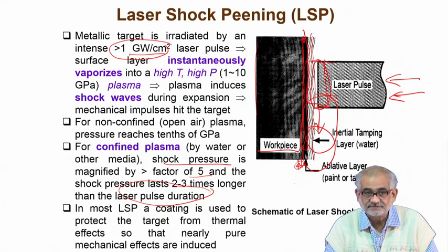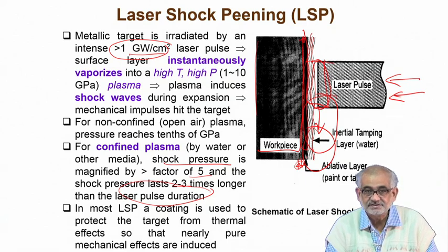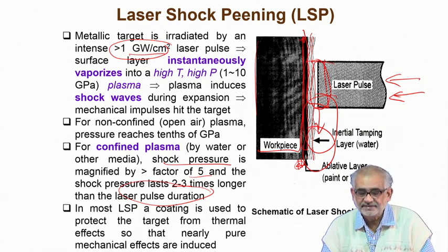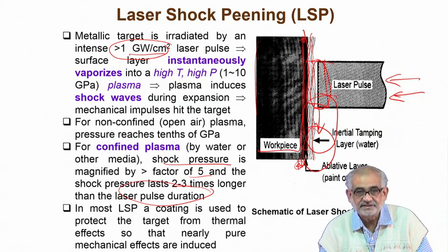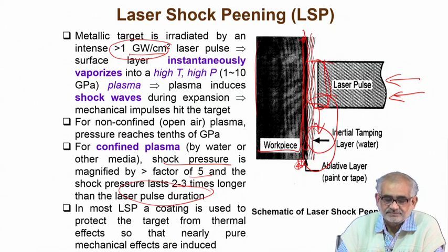It is not the thermal effect of the laser that is important or that makes changes on the surface of the work piece, but the shock wave generated because of rapid vaporization of the coating or thin film that has been applied and then covered with a tape or some other confinement mechanism.